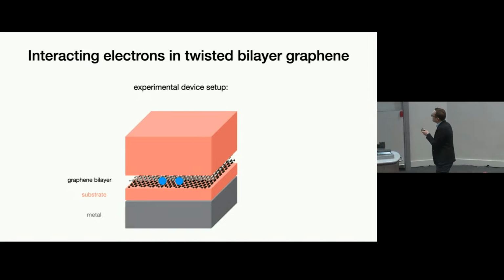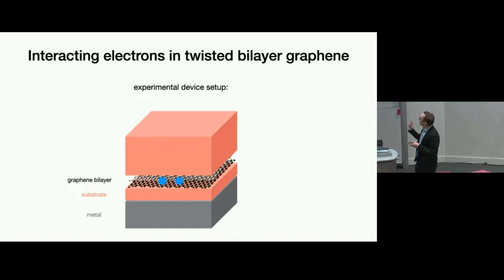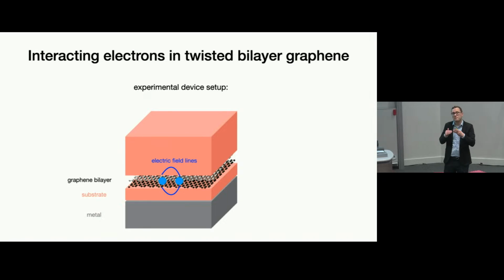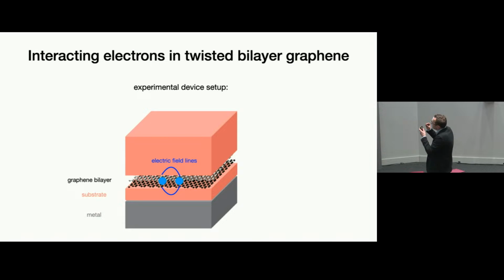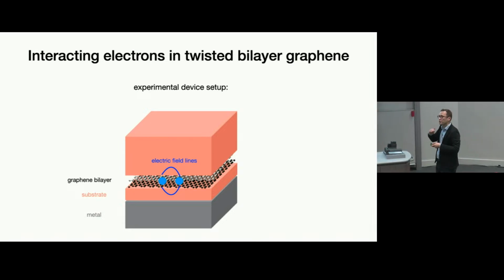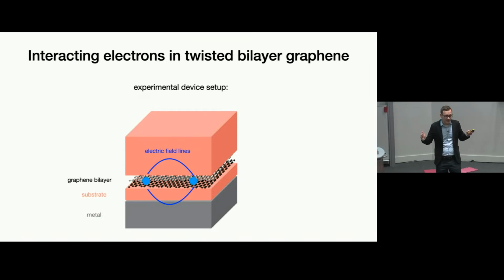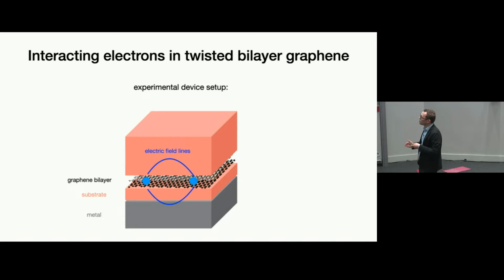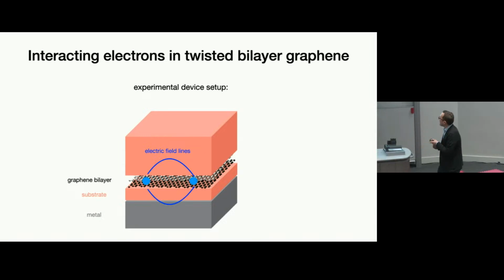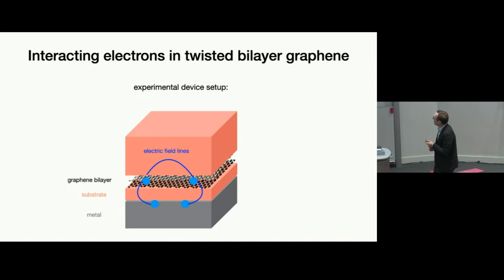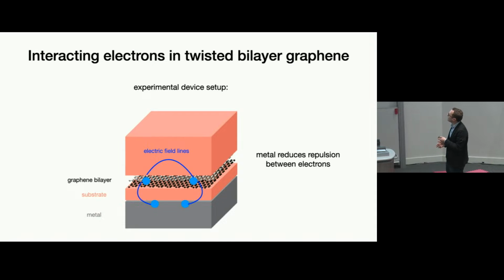Well, to understand that, let's see what happens when we put 2 electrons into the graphene. Now, these 2 electrons repel each other, and the strength of the repulsion is mediated by the electric field lines. Now, when these electrons are quite close to one another, these field lines stay quite close to the plane of the bilayer. Now, I already told you that actually we know that the wave function of the twisted bilayer graphene is huge, so these electrons are actually not very close to one another, and as a consequence, the electric field lines can actually stray very far from the plane of the twisted bilayer, so much that potentially they can even go through the metal. When that happens, the metal actually plays a role because the metal has also mobile electrons which can then interact with the electrons in the graphene, and that in turn weakens the repulsion between the 2 electrons in the graphene bilayer.